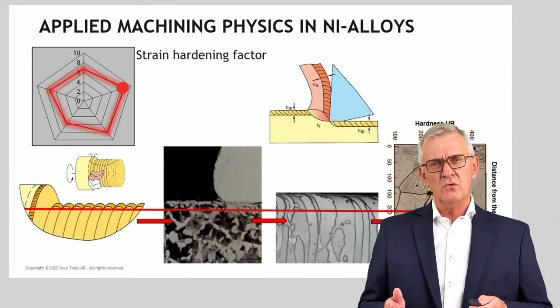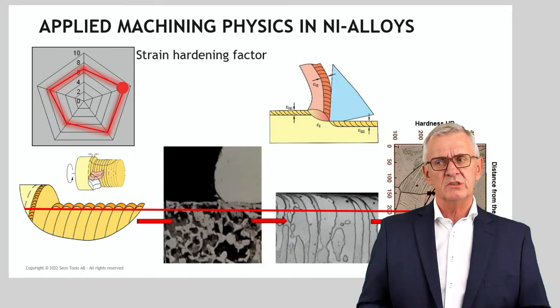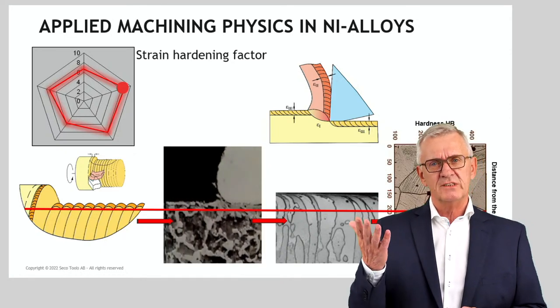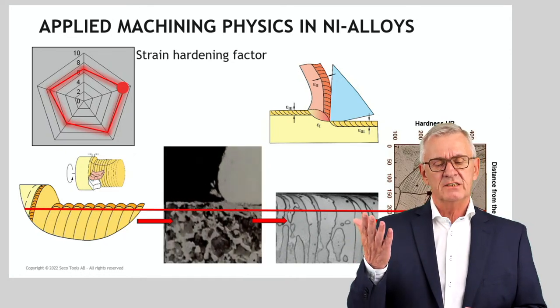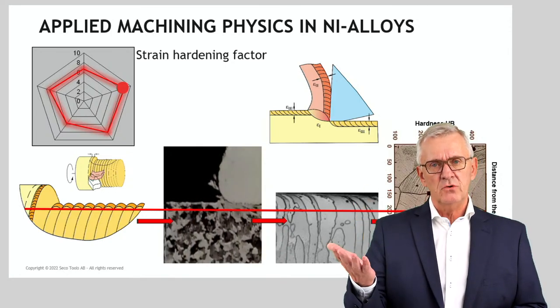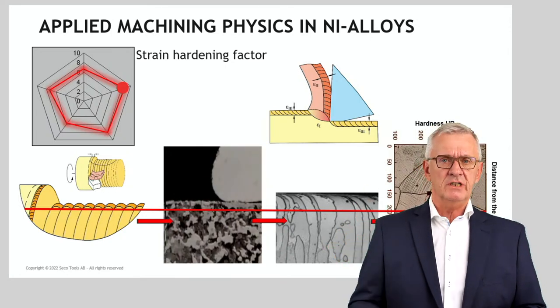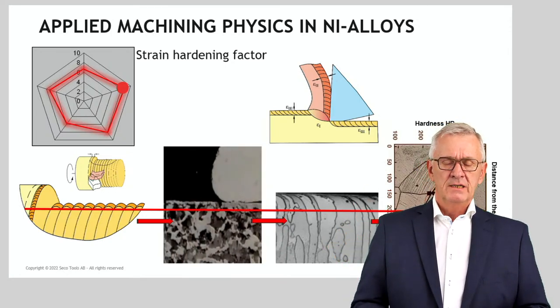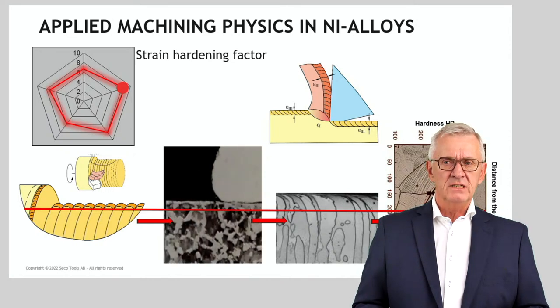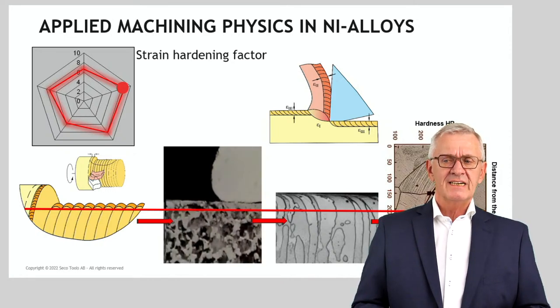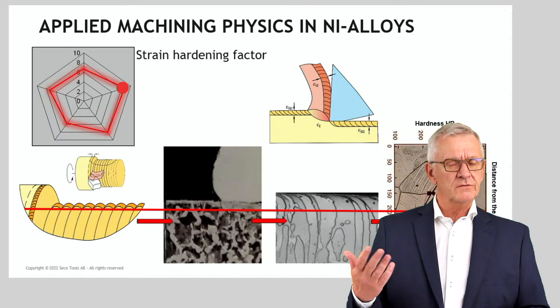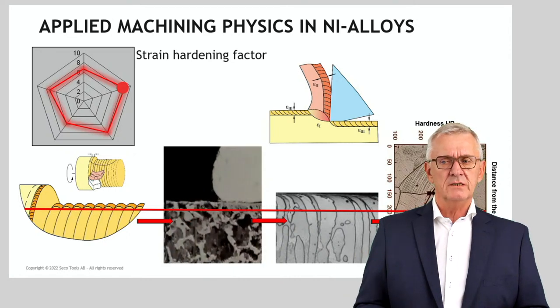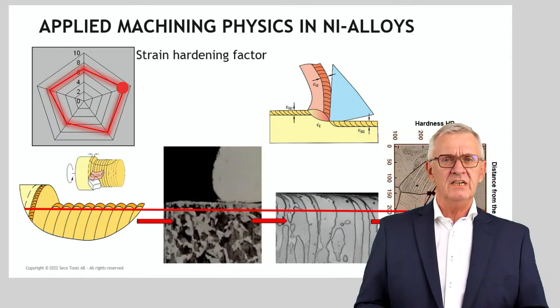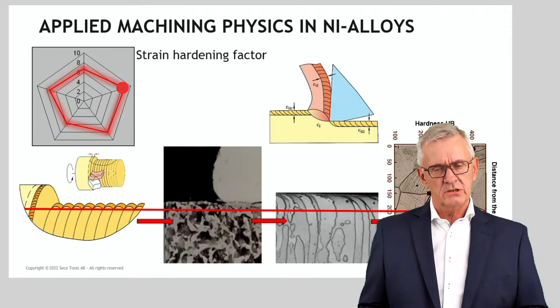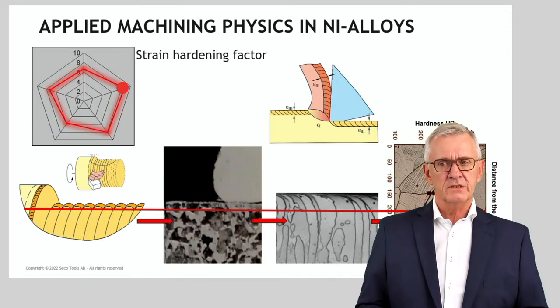And it is so important to realize this happens, because this very simple thing is the basis on which we select our cutting conditions. Strain hardening effects in nickel-based alloys are very important. You also find it in other materials, but in nickel-based materials, it could really be a killer of cutting edges, if you are not aware of this.